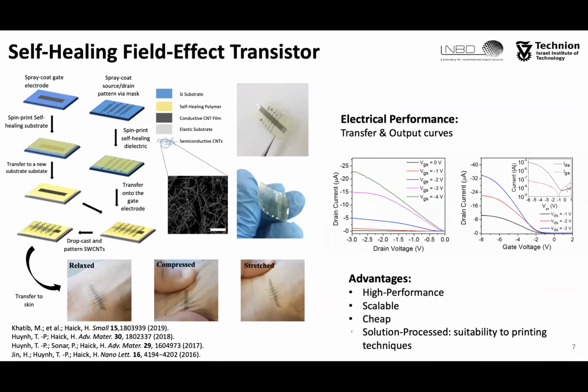The self-healing of the polymer, which we examined back then, allowed the so-called induced recovery of the ultra-thin carbon nanotube films, and all the conductive components which you see on the right side of the slide of the FET, including source drain electrodes, gate, and semiconductive channel, showed good self-healing efficiency, which enabled the recovery of the whole transistor-like behavior even after severe cuts, even if cut completely.